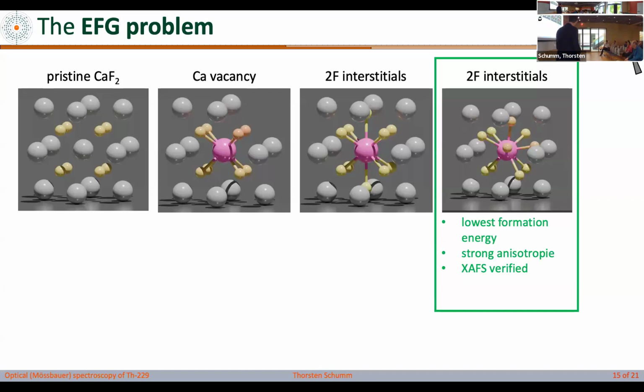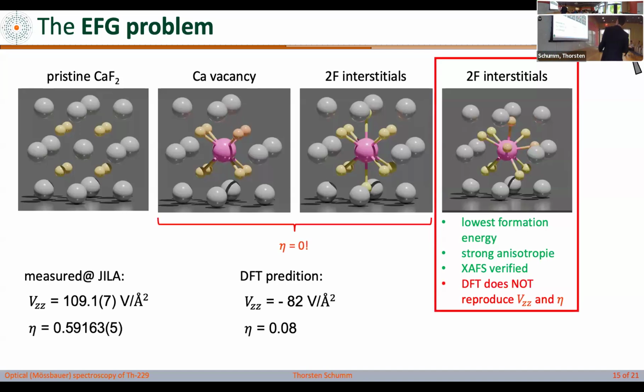Okay, so that's great. And the story could be over, but there's one big problem: the density functional theory actually gives us the electric field gradient and the anisotropy parameter, and it doesn't fit the experimental one. Not at all. Not closely, but really not at all. And we don't understand that.